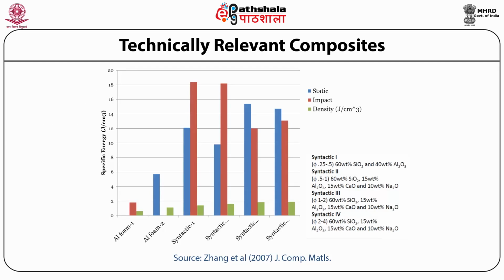This is the bar graph which shows the variation for the specific energy for the different composites, which are represented as aluminium foam 1, aluminium foam 2, syntactic 1, second, third, and fourth. Now here the blue one corresponds to the static, the red the impact, and the green one corresponds to the density. So the maximum impact and the static corresponds to syntactic first, having the composition of 60 weight percentage of SiO2 and 40 weight percentage of